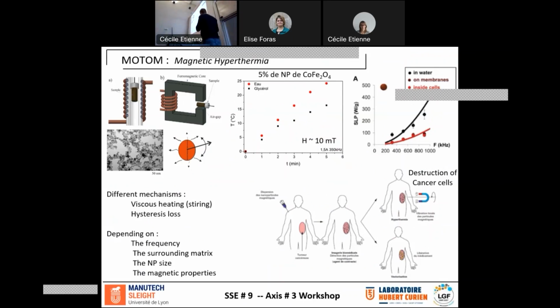So what is the mechanism? The mechanism in liquid is that the particles can move. So you can induce a stirring of the nanoparticles in the liquid. So this is a viscous heating. And of course, we have some magnetic hysteresis loss. So the mechanism, of course, depends on the frequency. If you increase the frequency, you increase the effect. It depends on the size, it depends on the magnetic properties. At the time, that kind of phenomenon is planned to be used to destroy cancer cells, because you can fix the particles and increase the temperature.